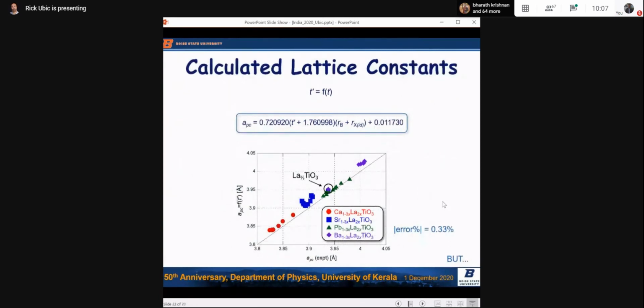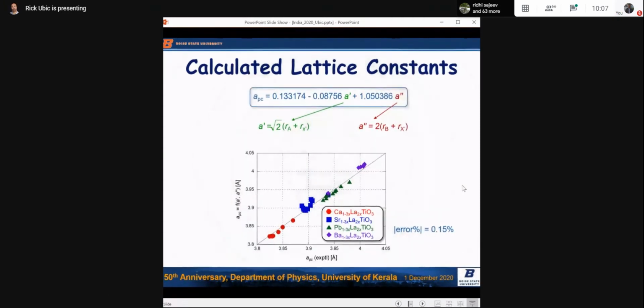When we apply it using T prime as a function of tolerance factor, we get this equation, we graph it, we get this. The average error is 0.33% for the perovskites I showed you on the other graph that we derived it for. But remember, we get 2 other ways of calculating lattice constant. We have A prime and double prime still, right? So we can do a linear regression again and graph A as a function of both those things, and we get an average error of just 0.15%.